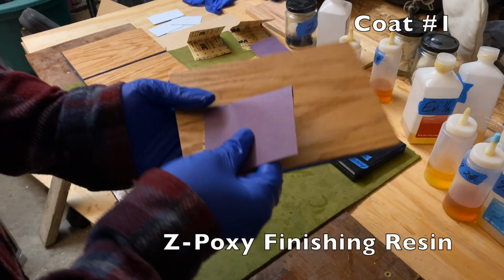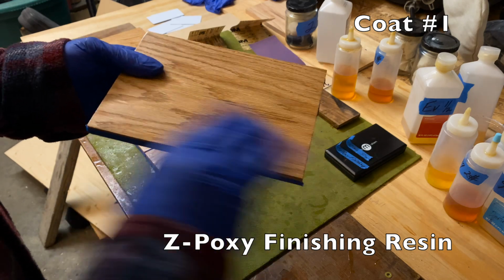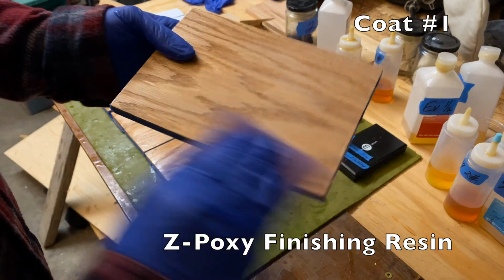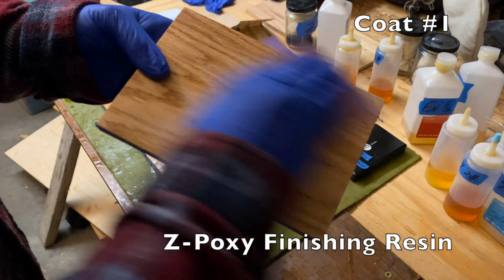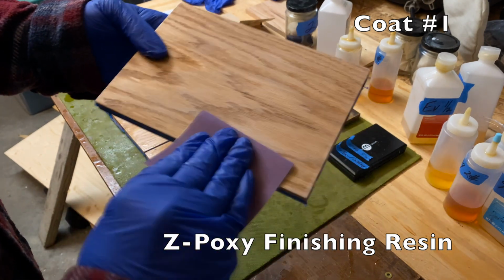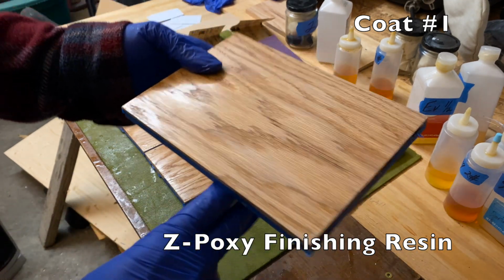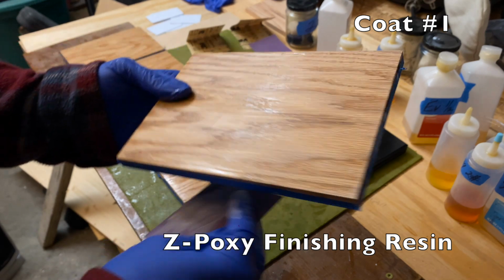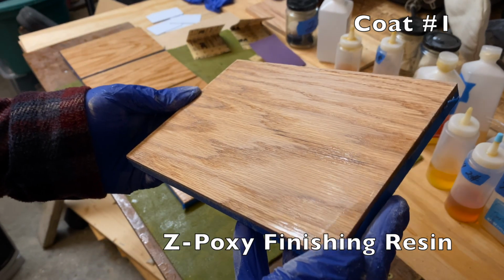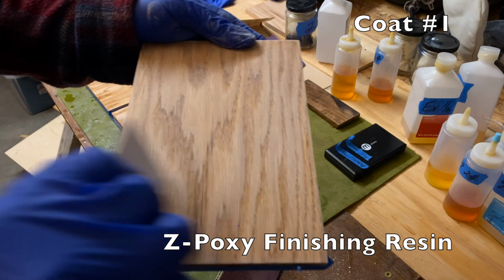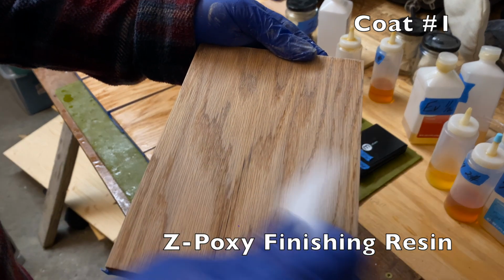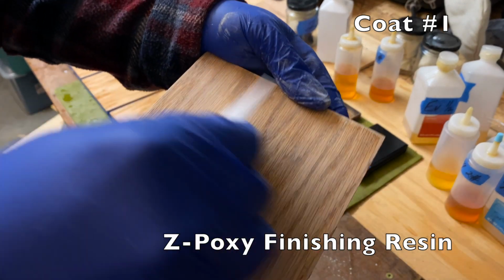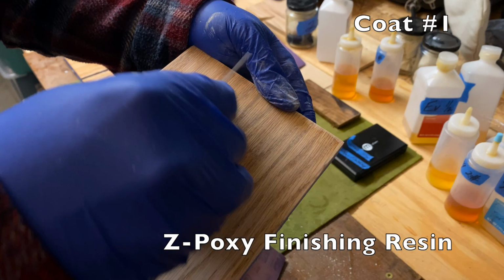So I'm going to start sanding these boards by hand using 320 grit sandpaper just to see how the dried epoxy responds and how much effort is needed. Normally I'd just pull out the orbital sander with some 220 grit paper and be done with it, but I'm curious about the nuances of sanding these epoxies. And the Z-poxy finishing resin responded pretty well to the 320 grit sandpaper, which is nice because it's advertised as being easy to sand.